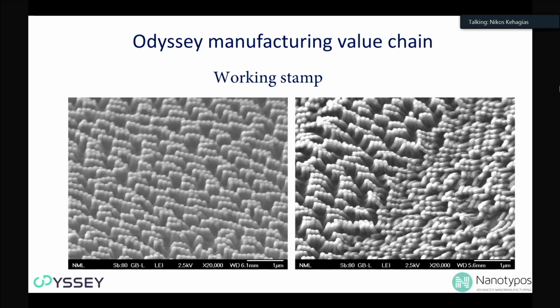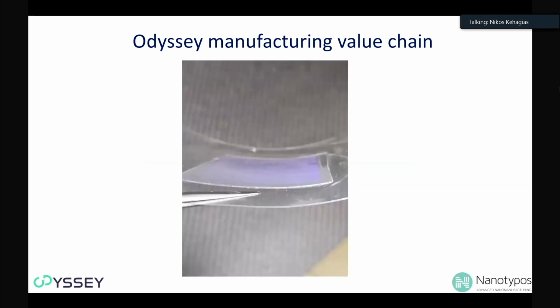So the other thing is that, okay, we had our material. How do we replicate? Is it very straightforward to replicate such high aspect ratio structures? In the first experiments, we saw that it was not an easy task. So we got phenomena like the collapsing of the pillars and them attaching and making all these aggregations. So working slowly and developing the printing parameters, the chemical parameters of the material of which the stamp is made, and also of the embossed material, which is also a key point, we did finally manage to get a large area. Large area means 3 by 3 square centimeter areas of a working stamp. This is a UV curable resist material which has been deposited on a PET substrate.